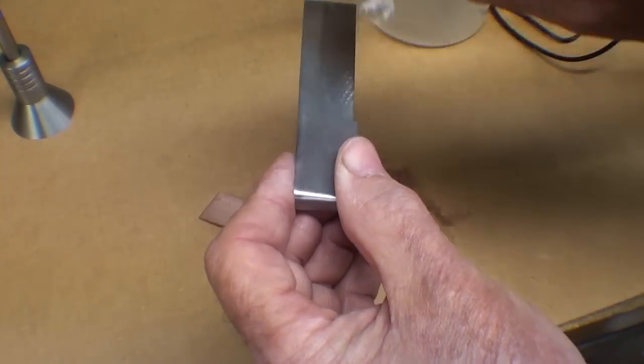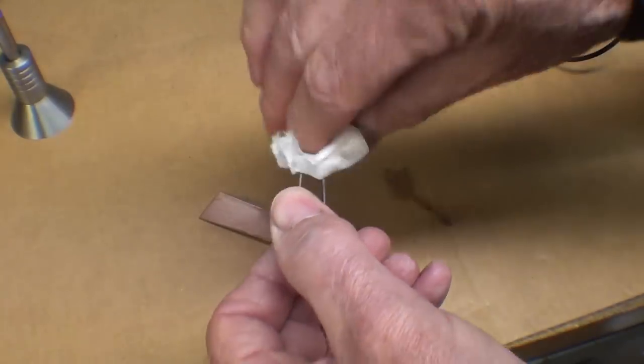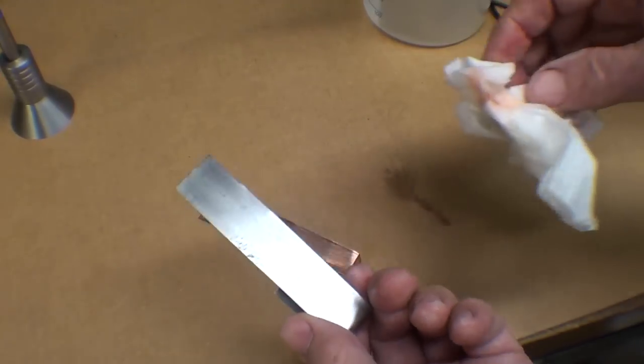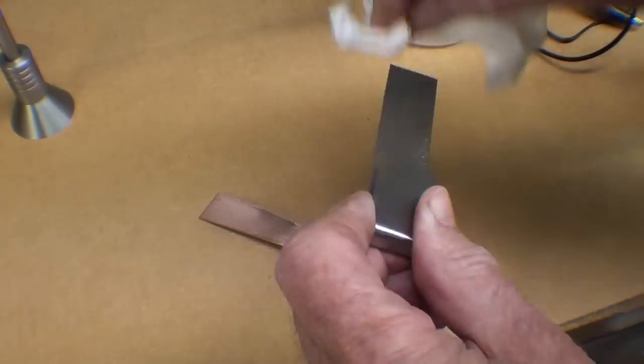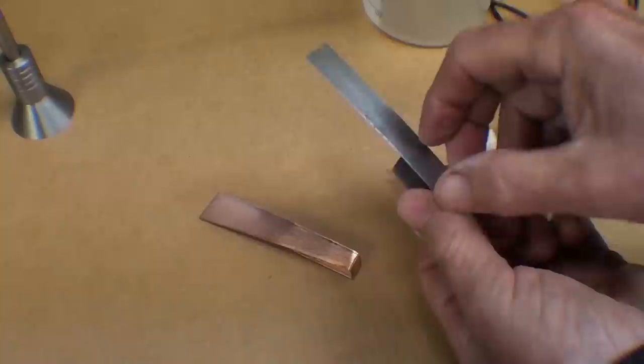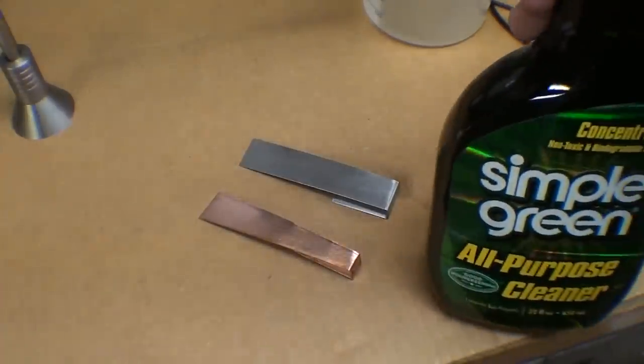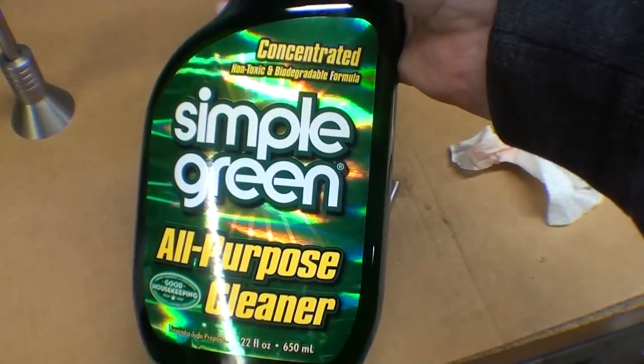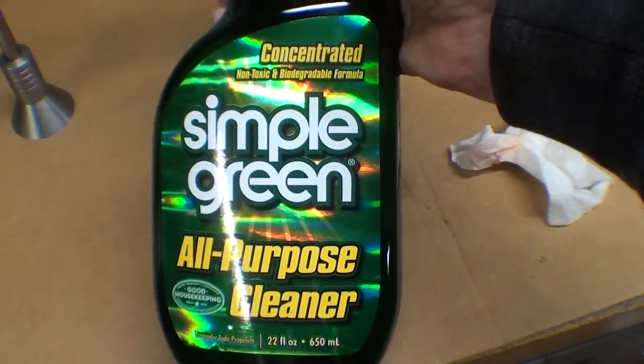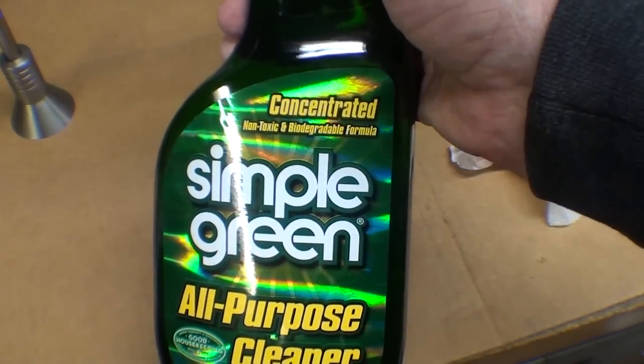You should never contaminate it by touching it. Now that's not good enough—that takes the oil off. Then finally, they said clean it thoroughly in detergent. That's about half of what they were doing in the plating plant—cleaning. They suggested Simple Green, which I guess is just a strong detergent. I'm going to clean it thoroughly with this and then dry it.